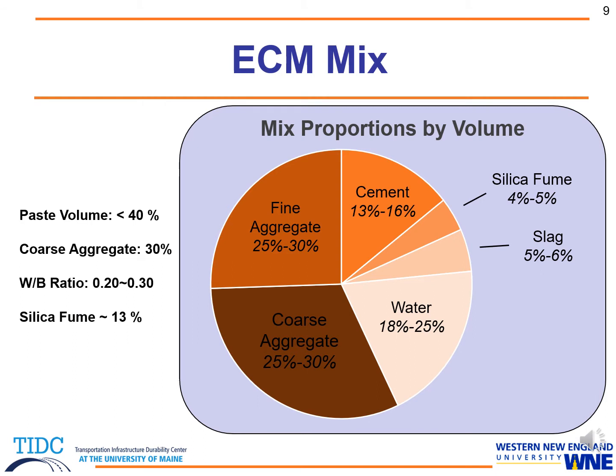Over the last 2 years, we've created very many different ECM mix proportions. The graphic on the right shows our mix proportions by volume, and this is just an overall general range that we've followed for all of our mixes. So to start off, by the end of our research, we've narrowed down our paste volume to be less than 40%,